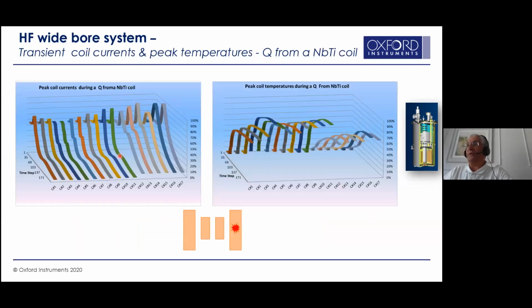One important aspect to look at is how these affect the hotspot. In this particular scenario, when we have a quench in the outer coil, we can see the impact on every single coil within the magnet. These are ribbons showing the transients on high temperature within the magnet, which is within the design guidelines. At the same time, you can see the transient currents within these coils building up in the coil with quenching, and the NbTi coils are not exceeding their design guideline. This is the most critical element, to ensure that when you have a quench, it doesn't push the stress and the voltages outside your design criteria.